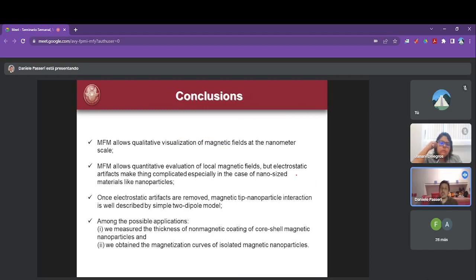So, just to conclude, I tried to convince you that, no, it's not a matter of trying to convince, this is very obvious, that magnetic force microscopy allows the qualitative visualization of magnetic properties at the nanoscale, but also quantitative. And I tried to convince you that these quantitative measurements are more often than not limited by the presence of electrostatic artifacts, which are most relevant in the case of nano-sized material. But if you remove electrostatic artifacts, it seems that even very simple models work. So everything seems to go as it must be.